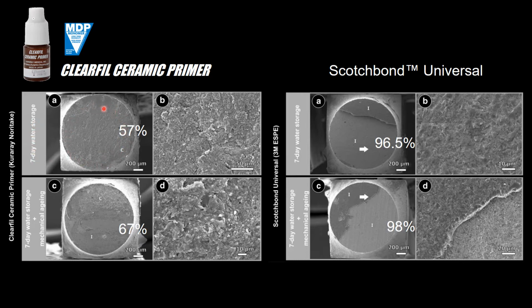The failure was in the composite cement. C is for when the cement failed within itself. In other words, the bond underneath was so strong that, 57% of the time, the composite cement itself gave. So the bond to the zirconia was stronger than the cement itself. And this is always a good sign when you're trying to bond something. And then when they put it in 7 days of water and then the mechanical stressing that I just mentioned, 33% failed in the composite, and then at the interface of the zirconia was 67%. So you can still see it's grabbing onto that zirconia very well, and these were very high bonds.